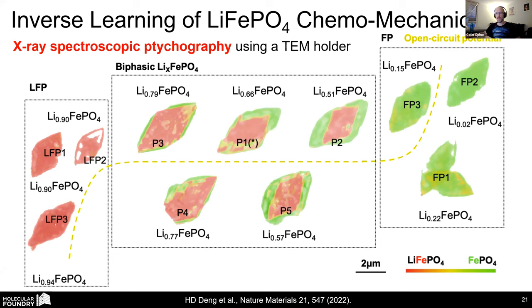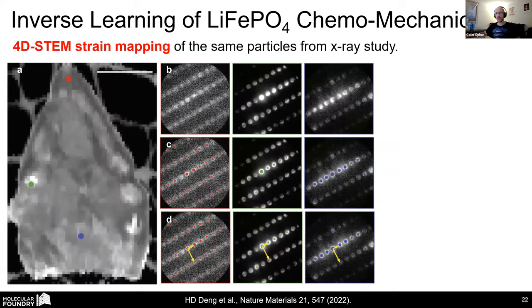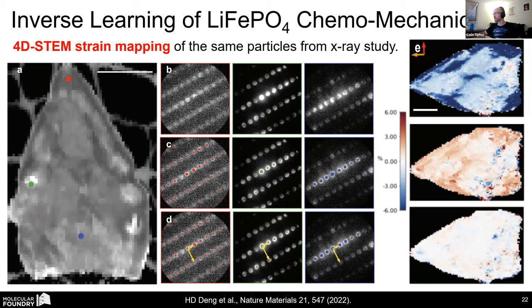So we can pop out the grids, the 3 millimeter grids, put them into our instrument and do 4D-STEM measurements of it. And it's a little bit thick. The diffraction patterns are a bit messy here, but you can see once again, from the spacing of these spots, we can easily measure the lattice constants. So I'm showing on the right-hand side here essentially the A and the C direction strains and then the shear strain in the bottom right.